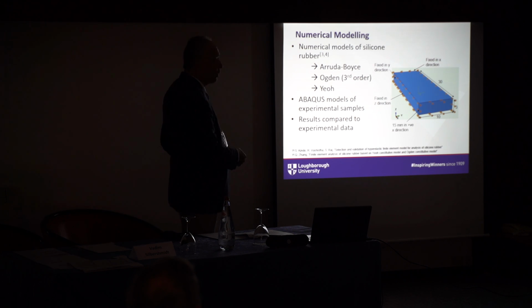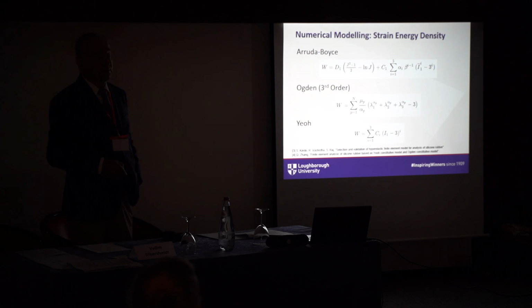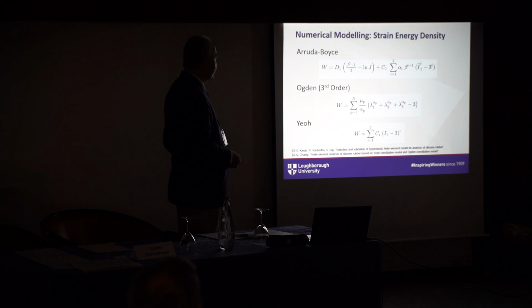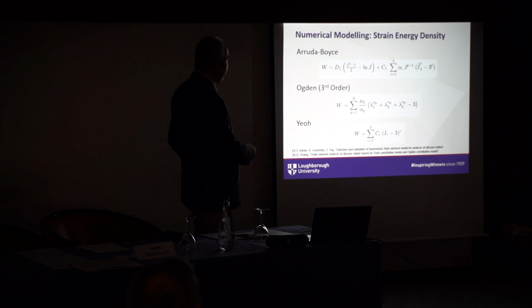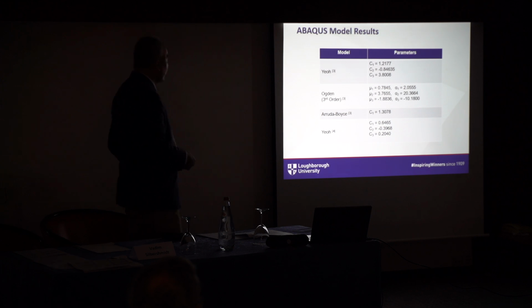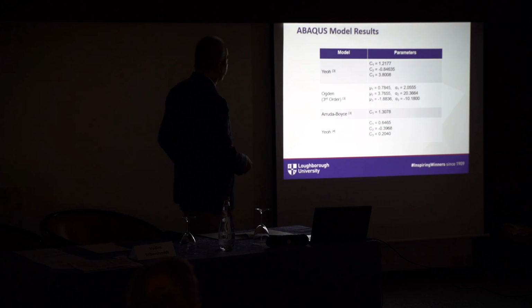We can also suggest using other tools which have a suitable set of models to be tested. Just once more, for those who are keen to get ideas about the equations behind all these models, these are three major potentials: Arruda-Boyce, third order Ogden and Yeoh. They are presented in a traditional way, and I'm not going into details here. Generally, these are the parameters for the material, and you can see that the number of parameters depends on the model together with the assumptions.